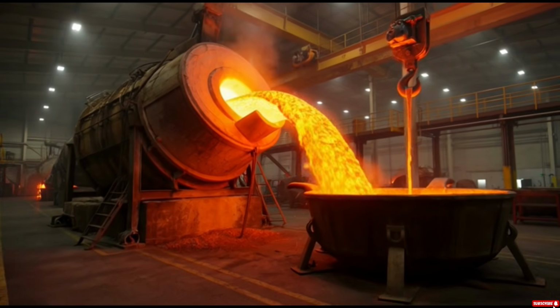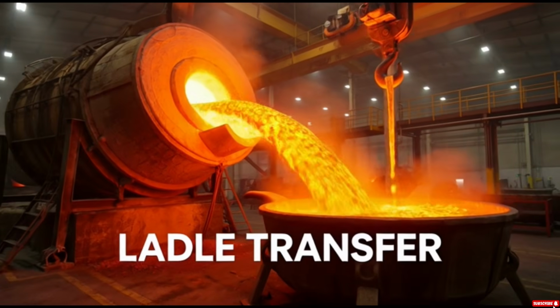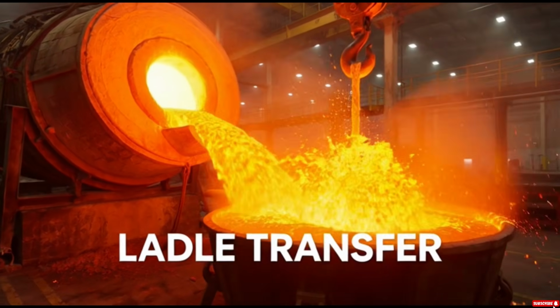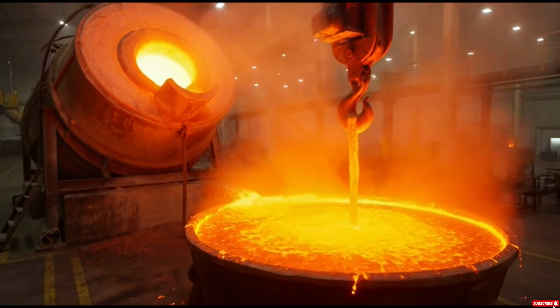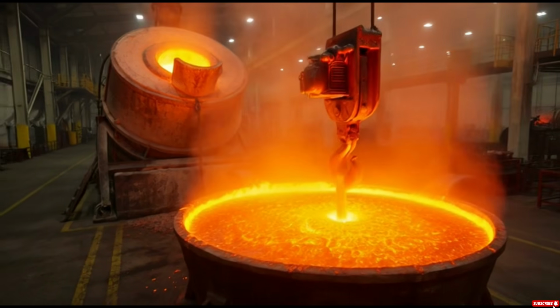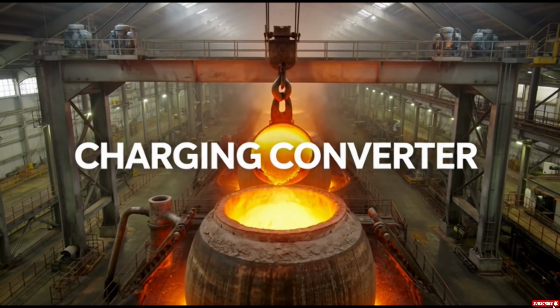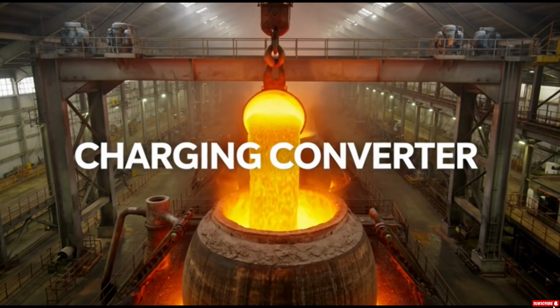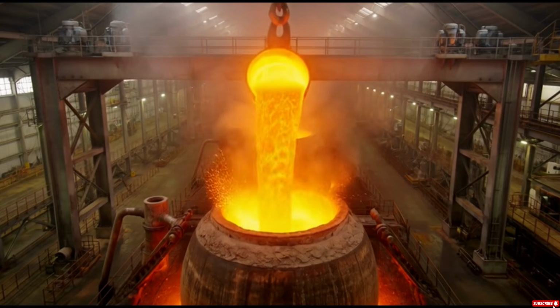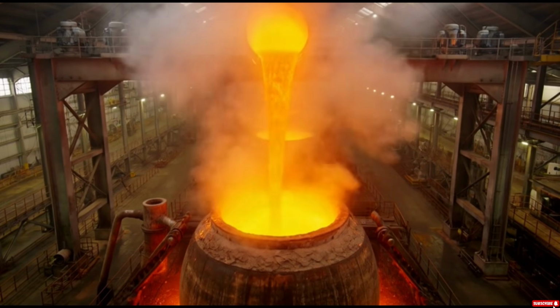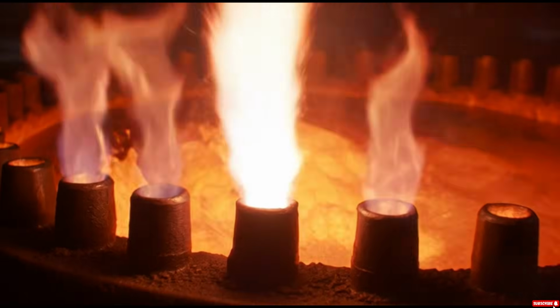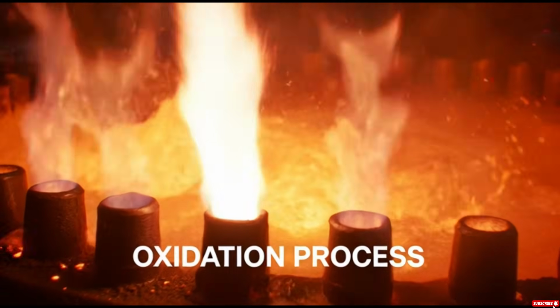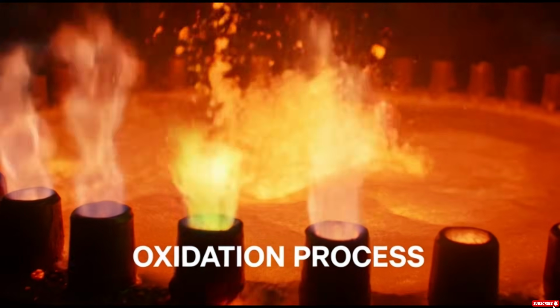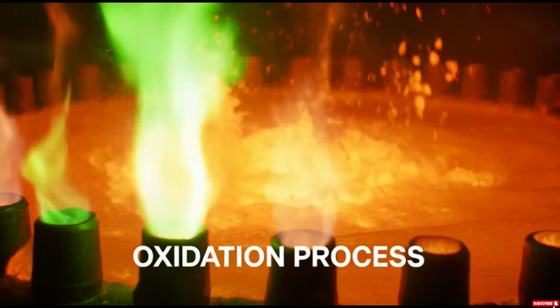We pour the molten matte into giant ladles. It's too hot to touch, over 1200 degrees. Next stop, the converter. We blow air through the liquid to burn off the iron and sulfur. The reaction is violent. Sulfur burns off as gas, which we capture to make sulfuric acid.